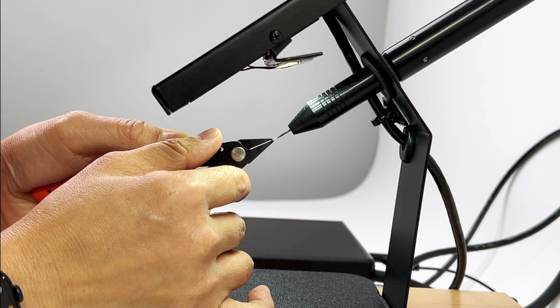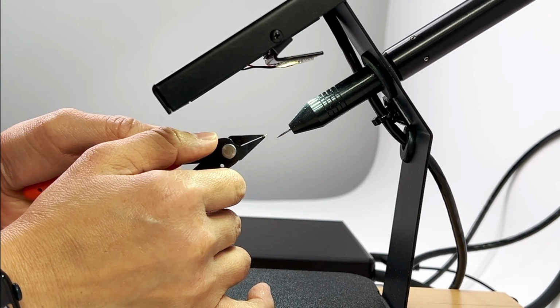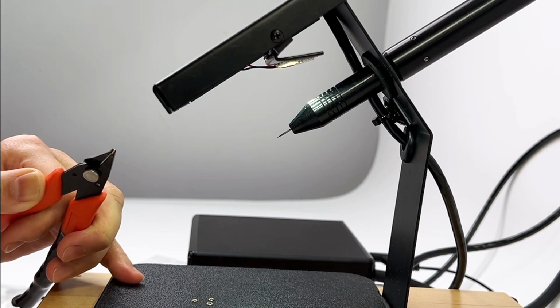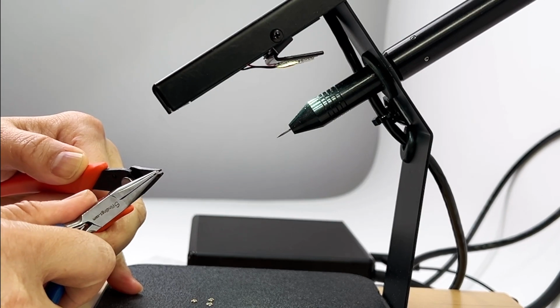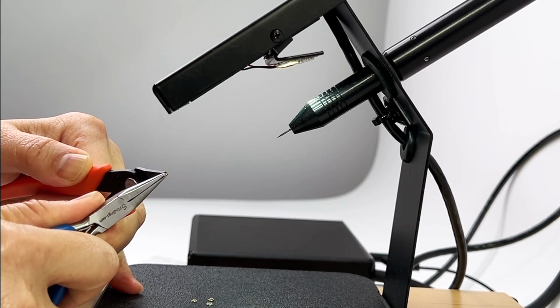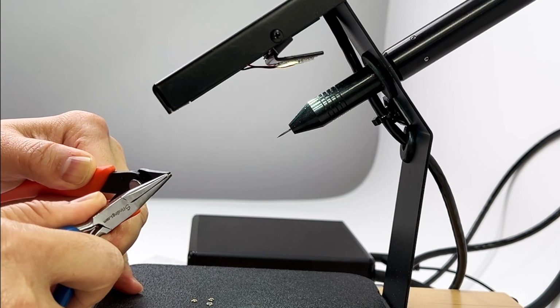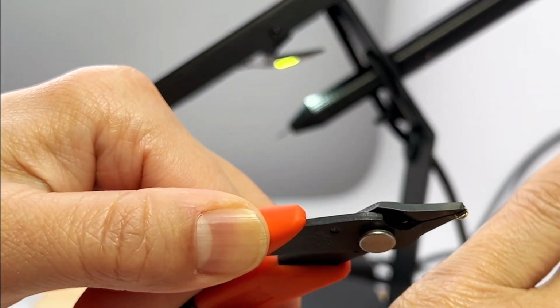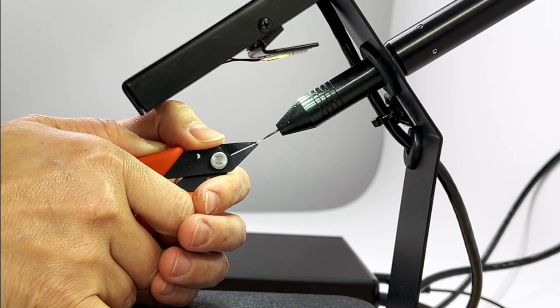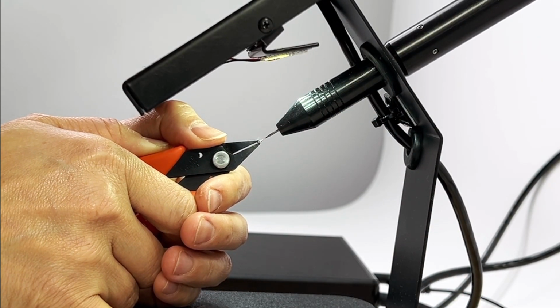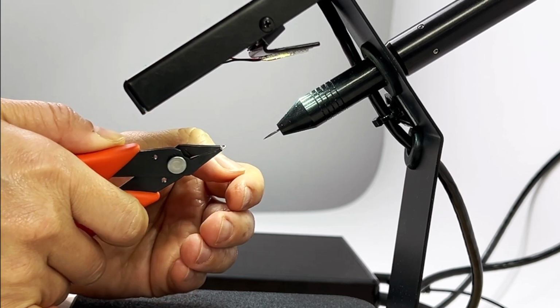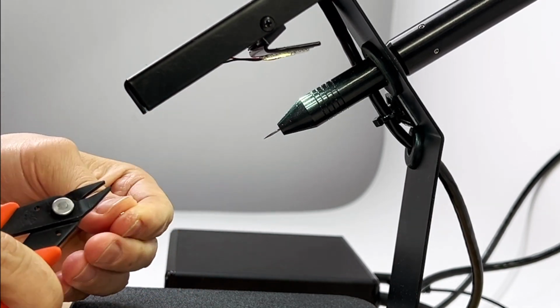I note the lowest power setting that I can successfully perform such a weld, and then I repeat the same weld with a new jump ring. And in this way, I know I can consistently replicate the result, and it's not a fluke. Also, sometimes with shaky hands and fine wire, the weld might not be perfect, and it's better to be able to get two samples and get an average idea of the performance level.